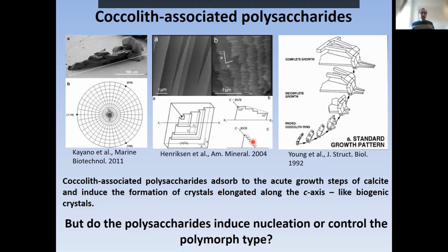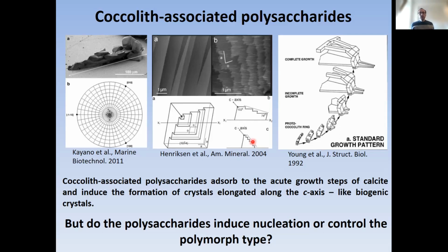The question that we're interested in answering is whether these polysaccharides can promote nucleation and whether they control the polymorph type. So calcium carbonate can grow into 3 different polymorphs, which means 3 different materials of different crystal structures. Calcite, which is the most stable one, and is what we found in coccoliths, but it can also form aragonite, which has a different crystal structure, it's slightly less stable, and vaterite, which is the least stable one. And we're interested in asking whether these polysaccharides can direct the formation of calcite, even in conditions that would favor the formation of other polymorphs.